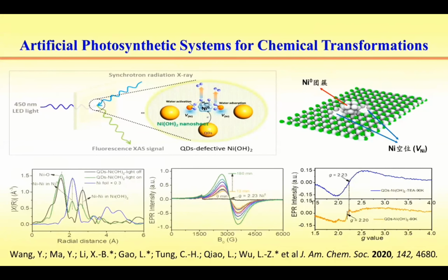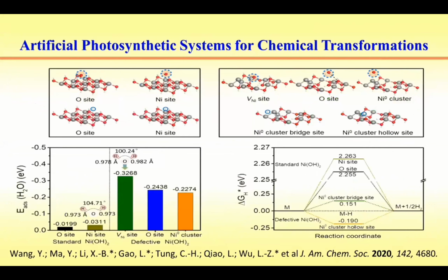DFT calculations show that water molecules interact with the nickel vacancies and the protons interact with the nickel clusters in this species for hydrogen evolution. Actually, the nickel clusters behave like the hydrogen evolution site, thereby promoting the activity of photogenerated hydrogen production in the alkaline medium.